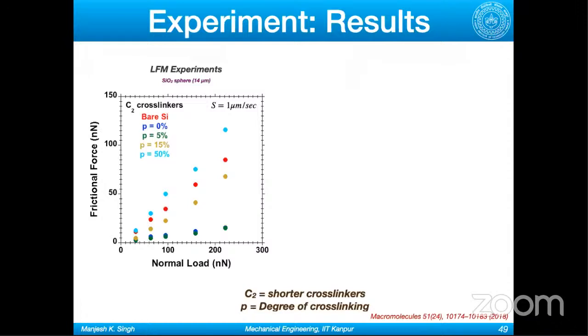So here are my results. The first one, the red one, is the bare silica. When I did a silica sphere against a bare silica surface, with no polymer brush, no polymer gels, we got a linear curve of friction force against normal load, which we expect. As soon as we grafted polymer chains, where P equal to 0 means zero degree, no cross-linkers, it's just polymer brush, you will see the friction force goes down by an order of magnitude. At the same normal load, you have very, very low friction force. So as I said, polymer brushes help you to reduce the friction.